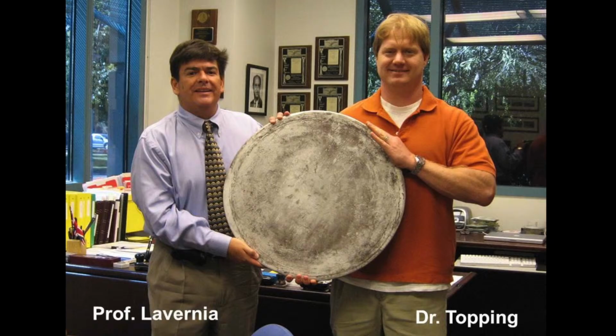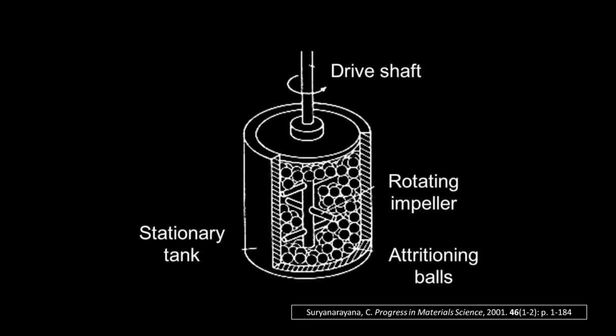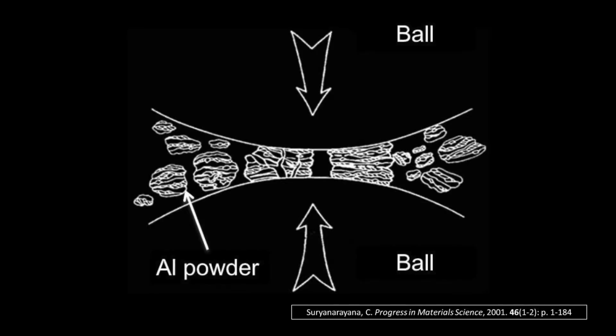In a collaboration with Professor Lavernia and Dr. Topping at UC Davis, we have engineered the microstructure of this aluminum alloy to improve its strength and toughness, creating an ultra-fine grain aluminum-based composite material. The grain size reduction was done by a modified ball milling technique under cryogenic temperature called cryomilling. The severe plastic deformation during milling breaks the grains into nanosize, and the low temperature prevents grain growth.